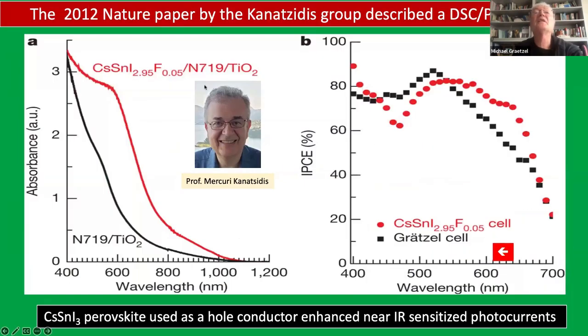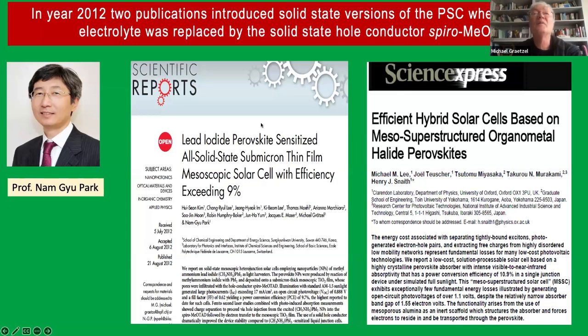There was an intermediate step that Professor Kanatzidis from Northwestern published in Nature, all in the same year. There were 3 papers published in 2012. And here he had kind of a hybrid, a dye-sensitized cell. So we had dye-sensitized TiO2, but he used a hole conductor that was a perovskite, a solid-state device. And so he found that perovskite did some co-sensitization. Then, these are not perovskite cells per se, they have no other absorber.